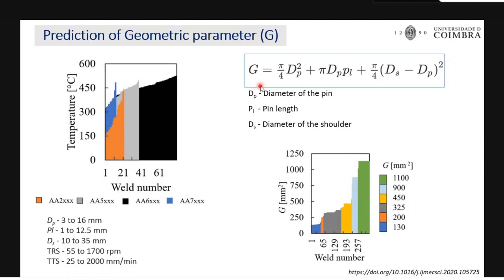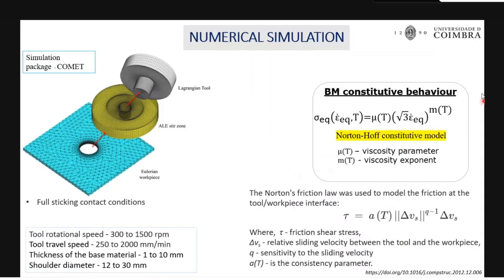And this is the G parameter, which uses the pin diameter, pin length, and shoulder diameter. I calculated the G parameter and found that people are using the G parameter from 130 to 1100 mm square. So I'm using that G parameter for the numerical simulation, and these are the details of the numerical simulations which were discussed previously.